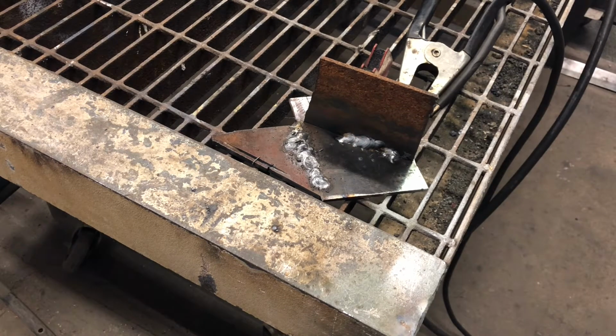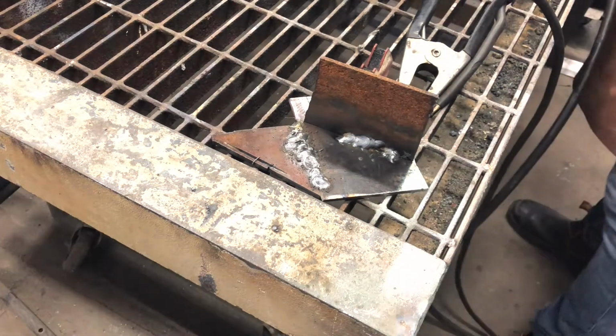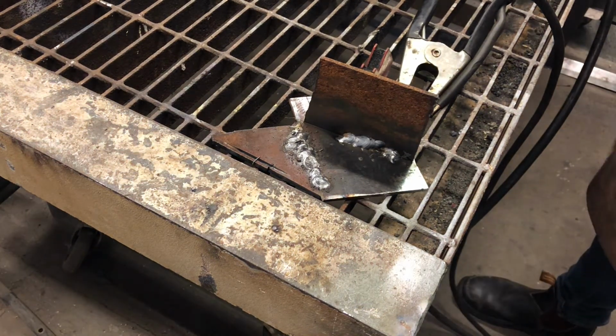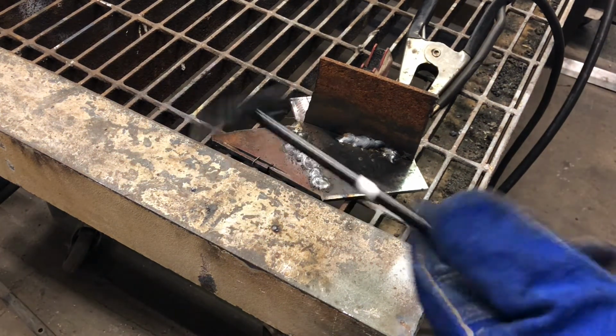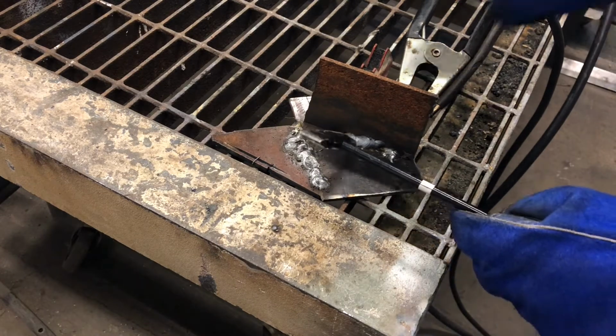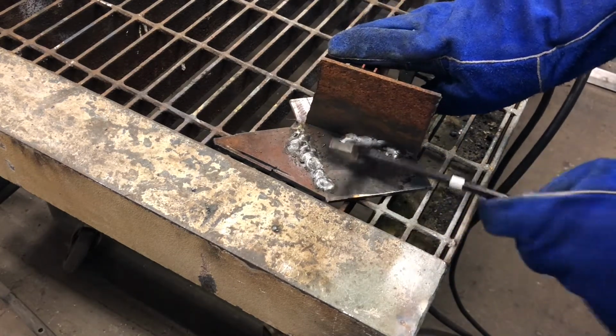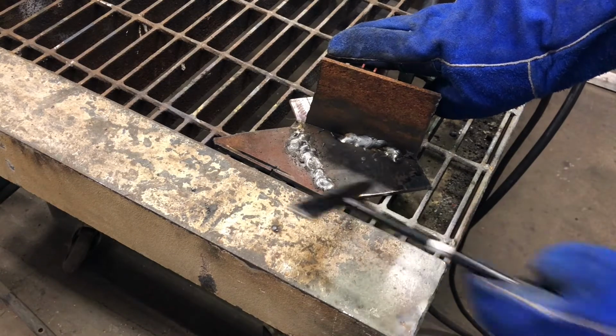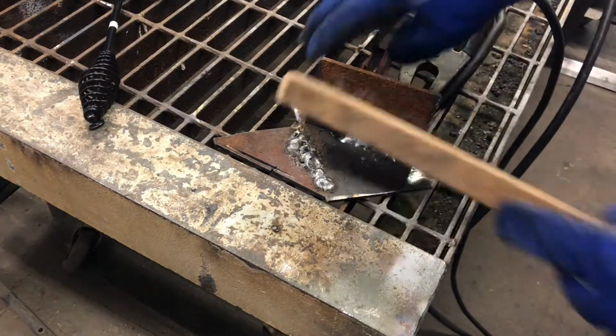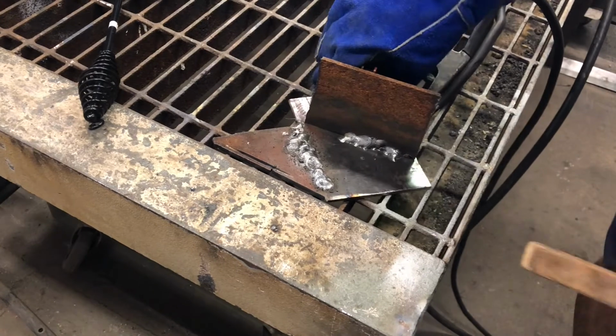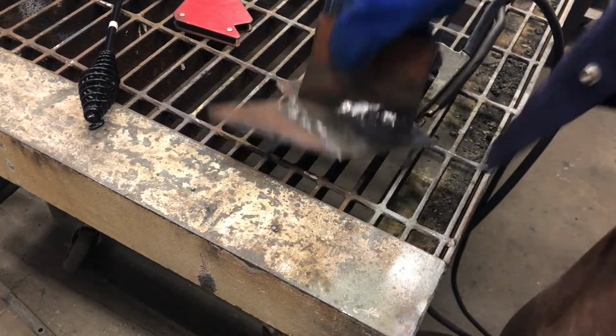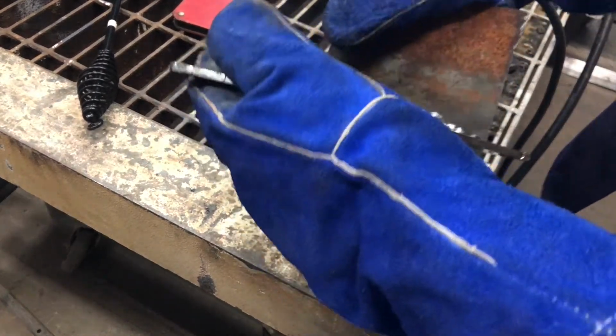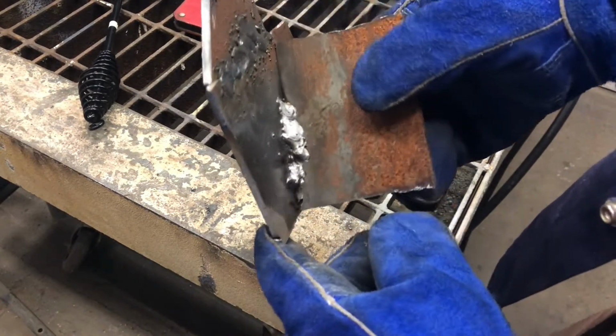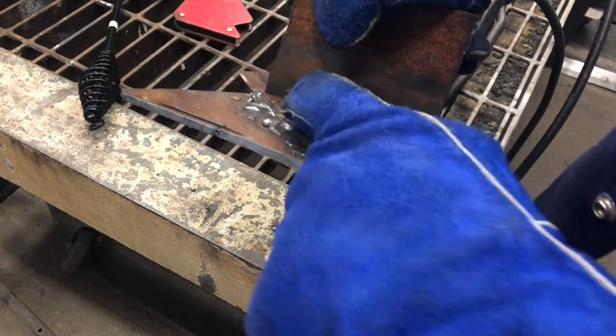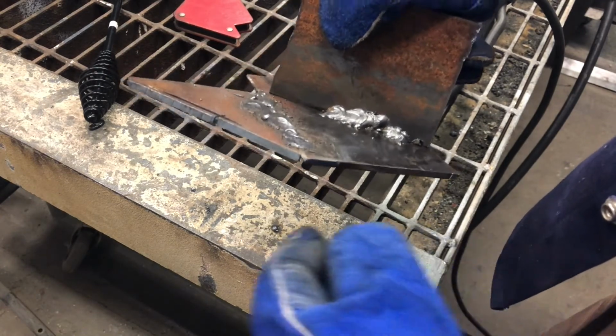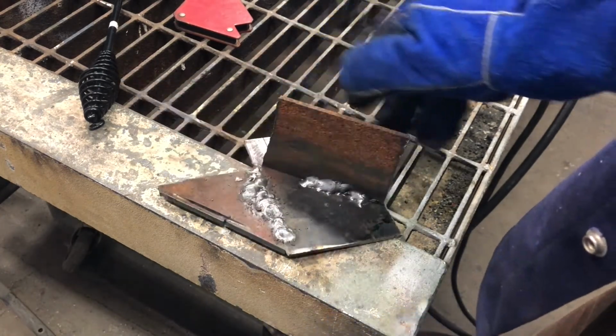As you can see, the MIG welder is so much easier than the arc welder. So now, I'm going to do the same thing. I'm going to use my slag hammer to see what my weld actually looks like. Actually, there's not even any coating on that like there is with the stick welder. That is just steel right in there. So that is stuck together. Now that's a pretty thick weld, but I could get in there with the angle grinder and clean it up a little bit.